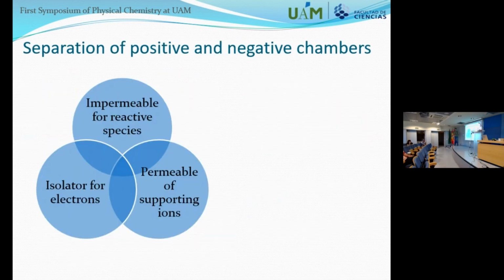As we said, we need to separate both chambers, and the membrane needs to have some specific requirements. The separator we are going to use needs to be impermeable to the reactive species, so we avoid crossover and mixing of them, but it has to be permeable to the supporting ions, because otherwise we couldn't balance the charges and it couldn't work. So we need both things at the same time, which is one of the main points of these separators. And of course it has to be an insulator for the electrons, to avoid a short circuit of the electrical circuit.